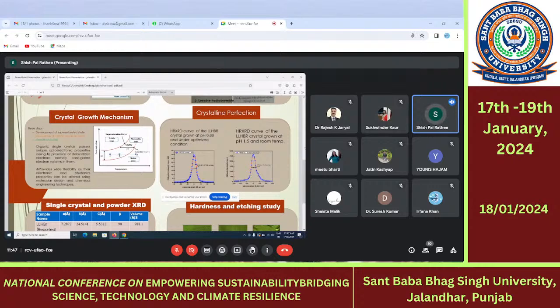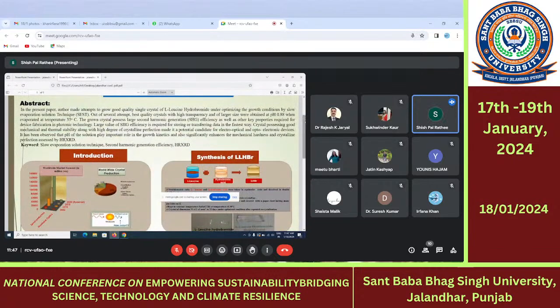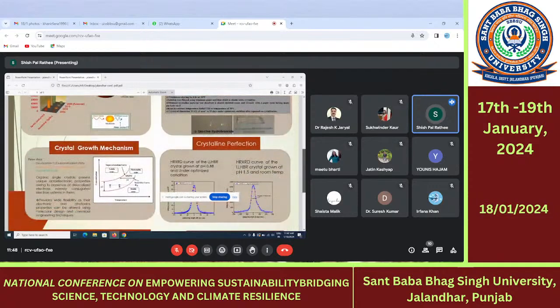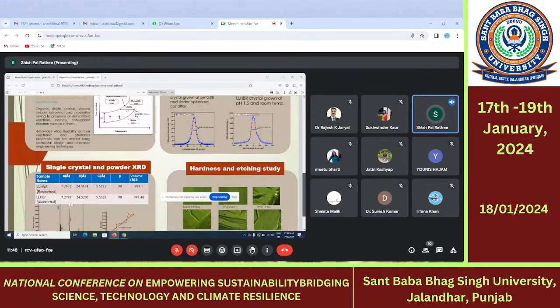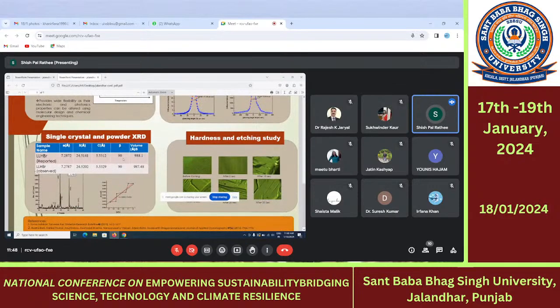The synthesized salt was analyzed by single crystal XRD, and the results of single crystal XRD almost exactly match the reported values with the observed values of this crystal.